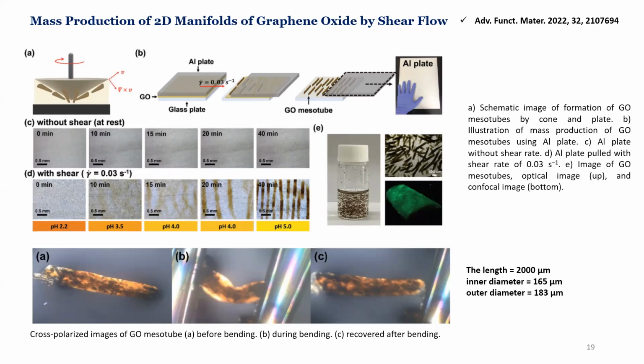The mechanism that we explained like this. At the pH 2.2, carboxylic acid groups of graphene oxide are protonated. At those pHs, aluminum can reduce hydrogen ions, which leads to an increase in the pH. So the carboxyl groups deprotonate, and aluminum ions can act as a crosslinker between the sheets. So when the sheets are put together and the shear is applied, they can start rolling. The final pH was 5.